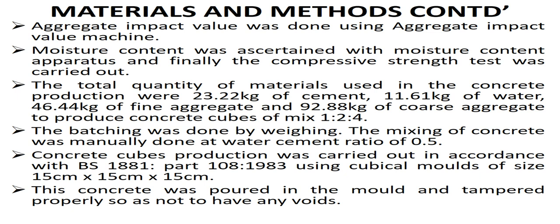The total quantity of materials used in the concrete production were 23.22 kg of cement, 11.61 kg of water, 46.44 kg of fine aggregate, and 92.88 kg of coarse aggregate to produce concrete mix of 1:2:4. The batching was done by weighing. The mixing of concrete was done manually at a water-cement ratio of 0.5. Concrete cubes production were carried out in accordance with BS 1881 Part 108 1983 using cubical molds of size 15 by 15 by 15 cm.